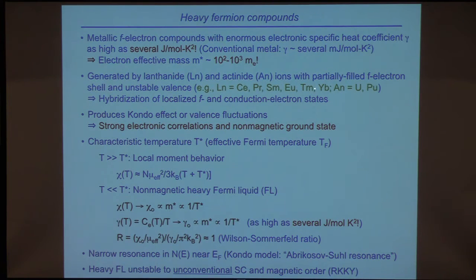And these are the lanthanide species where you find this type of behavior. And then you can also find it for uranium and plutonium. We don't work on plutonium, but we do work on uranium. And this gives rise to hybridization of these localized f and conduction electron states. And without going into the details, this can produce a Kondo effect or valence fluctuation type physics, which is characterized by strong electron correlations and produces a non-magnetic ground state in these materials.